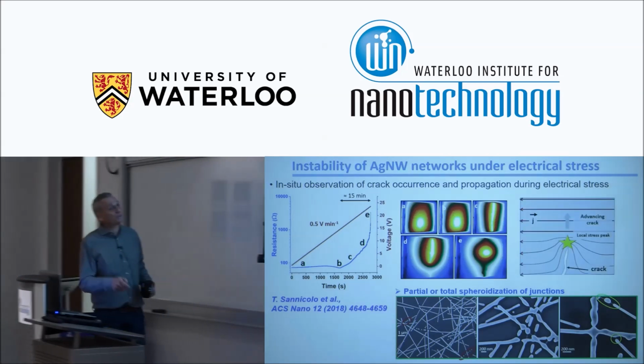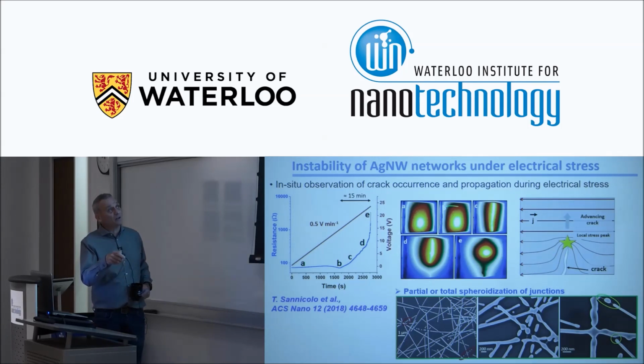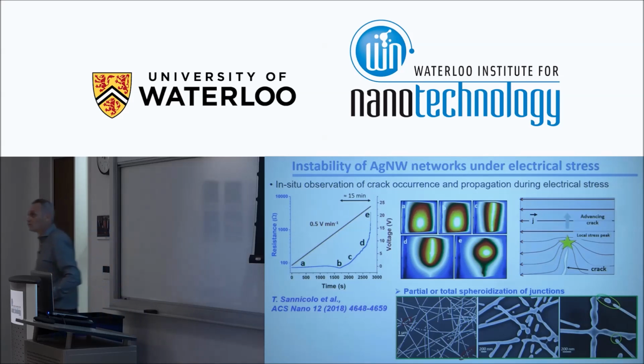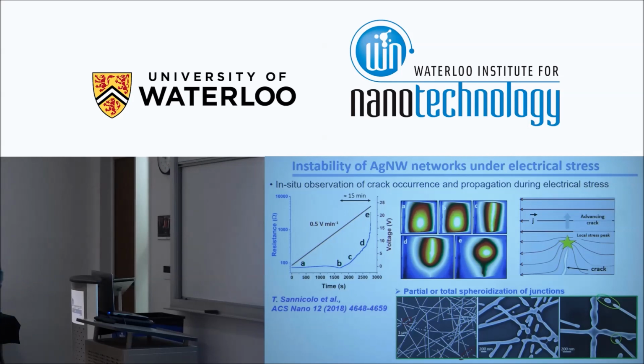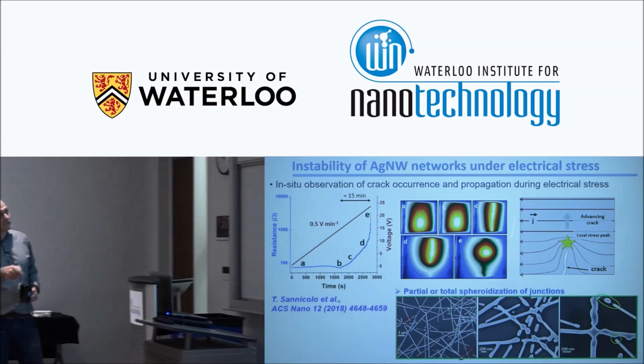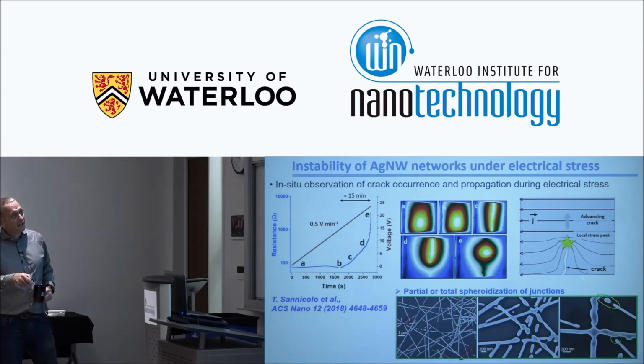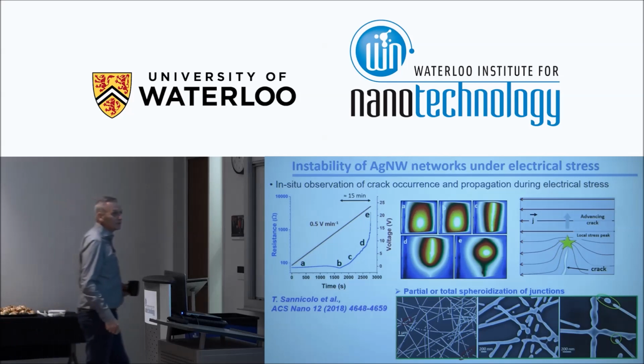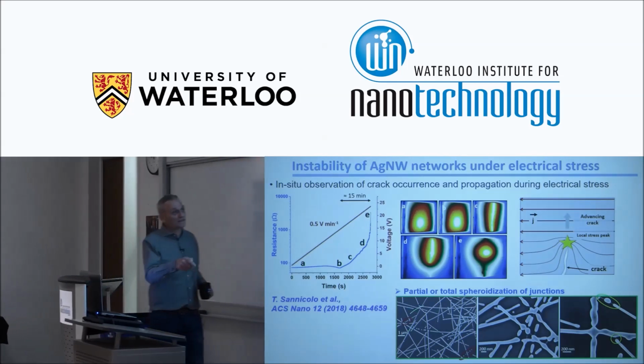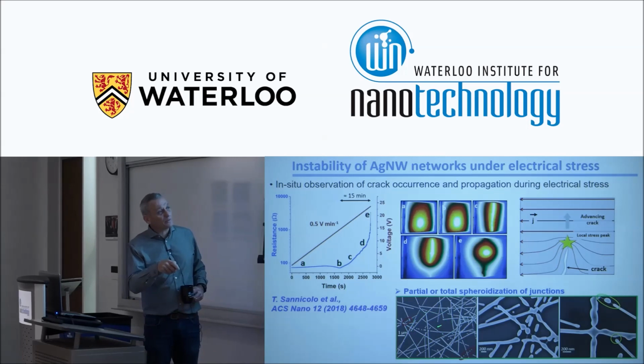And we observed this with an infrared camera. And we observed as well that there is a crack propagating. It's very analogous to mechanical cracking. There's a crack occurrence somewhere here. And since we apply a voltage difference between the vertical electrodes, there is a current density here. And here you have a concentration of current density. That means it's hotter here. And that is why the crack is going to propagate. And we can observe that easily with the infrared camera. And within the cracks, we can see that afterwards with SEM analysis.